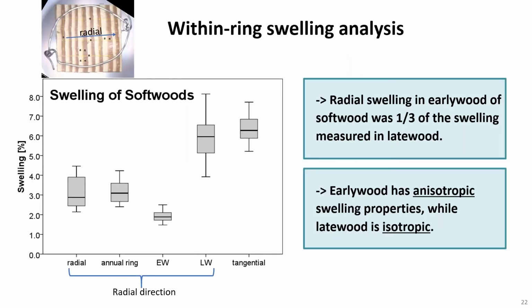And next, quite interesting graph, my understanding is this one. If you look at this picture at the upper left corner, you see this is Larix with the early wood and late wood, quite well visible. And it was measured like the whole radial distance, like that's what it says, radial. Then she measured individual rings, from the beginning of the early wood to the end of the late wood, and looked at the swelling there by comparing the different humidity moisture steps, images that we have taken during the course of sorption. Looking at the early wood only, which of course is bigger than the late wood, and the late wood, well, this is a quite distinct late wood here in that sample, but often late wood is, from the percentage, maybe 30% of the whole ring.